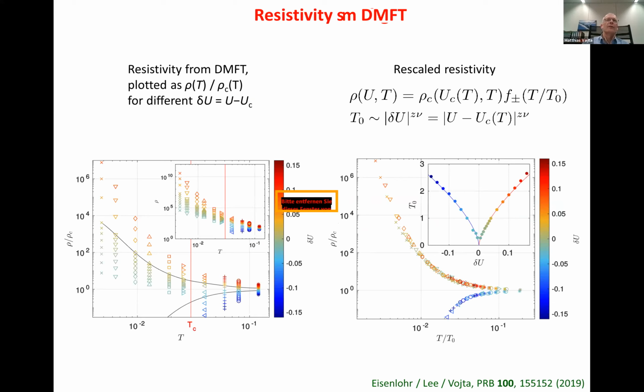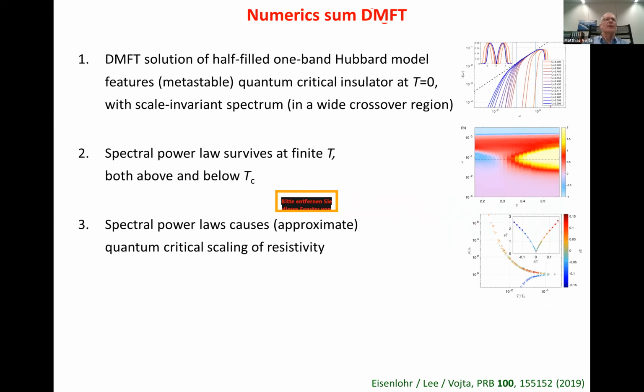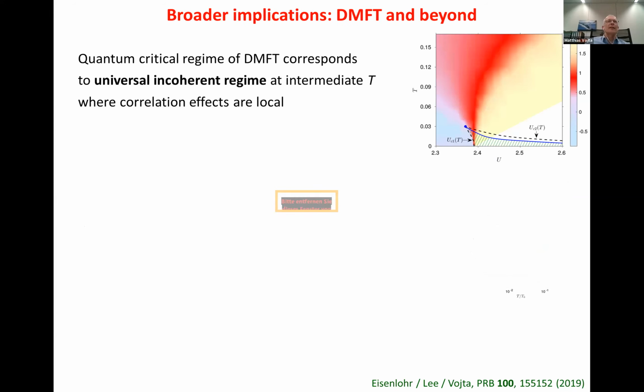Now, what did we achieve? Let me summarize the numerics here. We have seen that the dynamical mean field theory solution of the one-band Hubbard model has something which can be called quantum critical, namely this metastable insulator, which produces a scale-invariant spectrum and is responsible for this scaling of the resistivity. This means we have been able, at least on an operative level, to explain where this resistivity scaling comes from. Now, this raises a number of questions of a rather fundamental type.